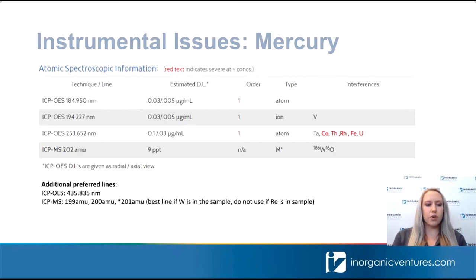And some additional masses for mass spec are the 199, 200, and 201 masses. The 202 mass, which is the one recommended in the table, does have a tungsten interference. So if you have tungsten in any of your solutions, make sure that you're not using that line. We recommend using the 201 mass as the best mass if you do have tungsten in the solutions, but be aware that there is a rhenium interference on the 201. So again, just make sure you're checking multiple masses or multiple wavelengths for each analyte to ensure that they're agreeing and that you're not seeing some sort of interference.